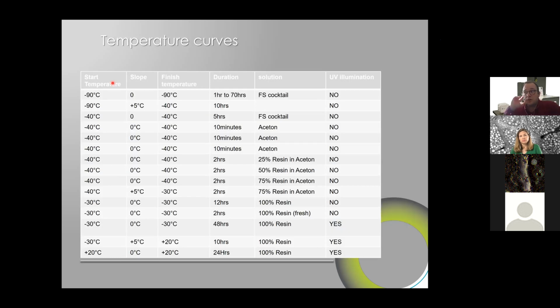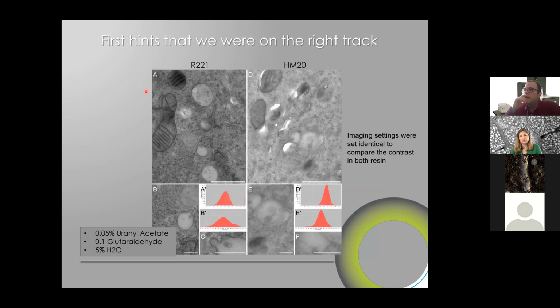Then the temperature curves, you will be familiar with that. This resembles a lot the Nixon and the Kukulski protocols. So basically starting at -90, going up to -40 degrees, at like 5 degrees temperature per hour. And then all of these steps, I think since you will have the video, you can always come back to this protocol in detail. And so we've done that over and over and over again.